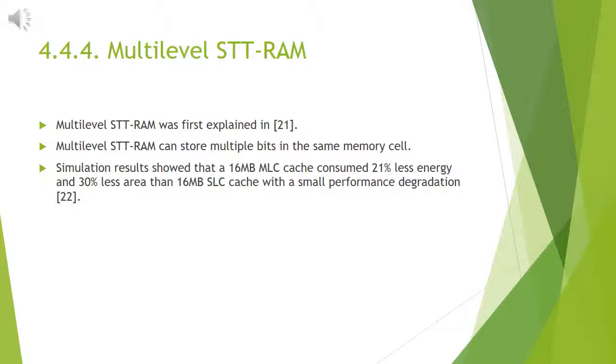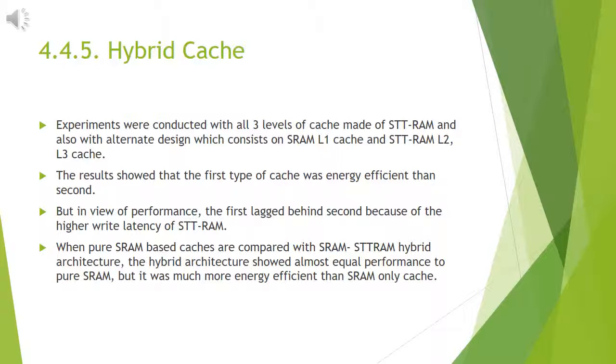The next method is multi-level STT-RAM. Multi-level STT-RAM can store multiple bits in the same memory cell. Simulation results showed that a 16 MB MLC cache consumed 21% less energy and 30% less area than 16 MB SLC cache.